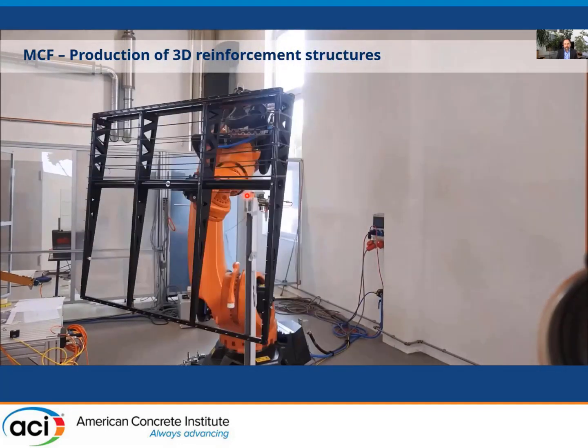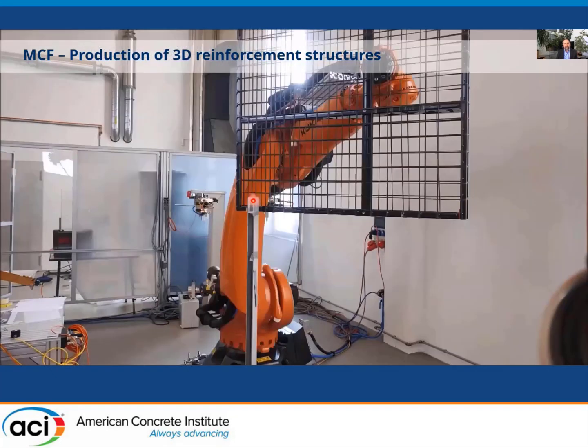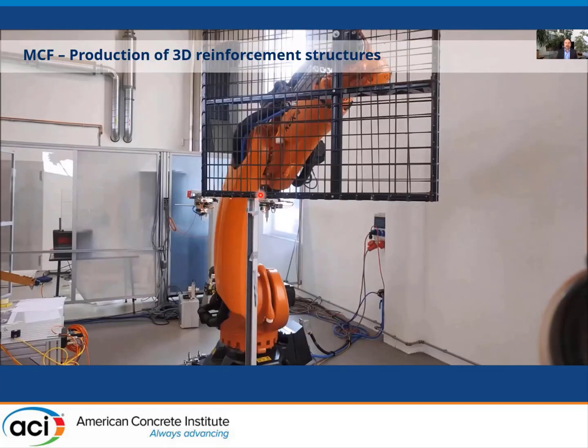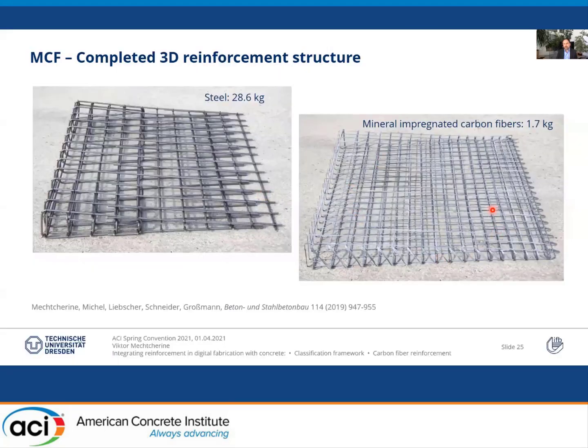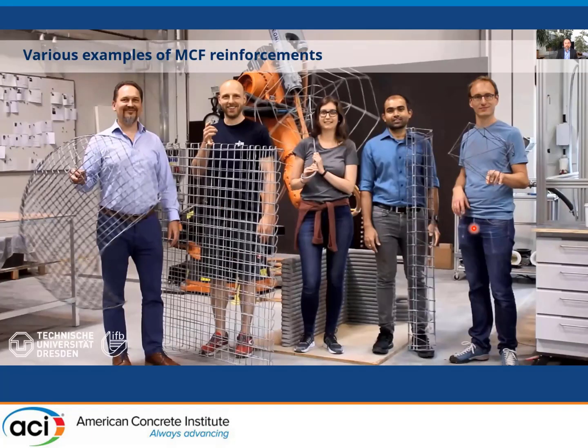The 3D reinforcement manufacturing is somewhat unusual: the print head stays in one place and we move the frame, wrapping yarns over it. At the end, we have a reinforcement cage that weighs less than one-tenth compared to a steel cage carrying the same loads — much lighter reinforcement. On top of that, it is non-corrosive, meaning the durability of such concrete structures would be much higher compared to steel-reinforced structures. Some members of my group proudly show you can even make an umbrella from this type of reinforcement.